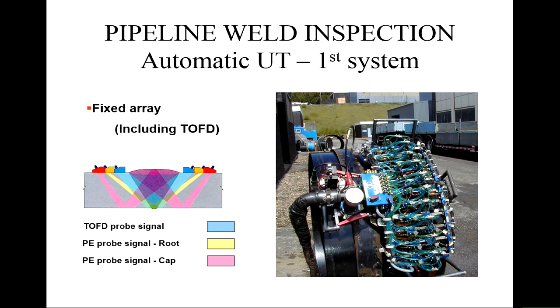Got three sensors on each side of the weld with different angles, and they're looking at three different parts. You've got time of flight probes, and you've got PE probes, and you've got detectors where you're getting a different signal coming back, and detectors where you're getting the same signal coming back. In this case, this setup relies on you having a transducer one side of the weld and a detector on the other side. So it's completely separate transduction and receiver. Other people try to use the same sensors, and there are advantages and disadvantages to each.